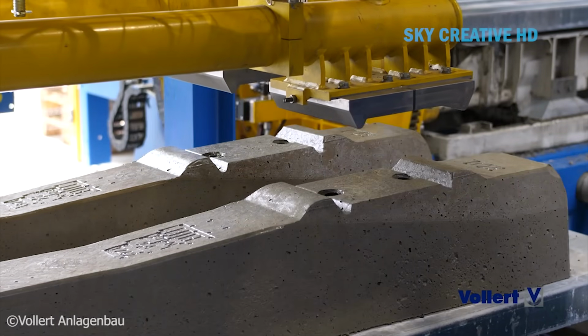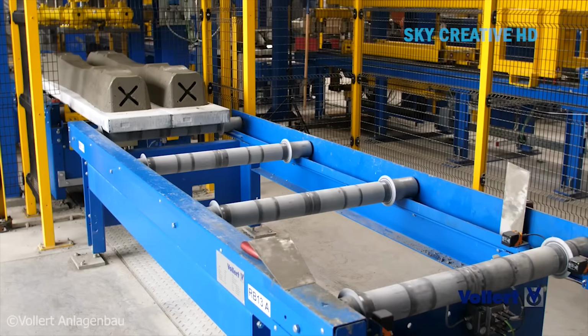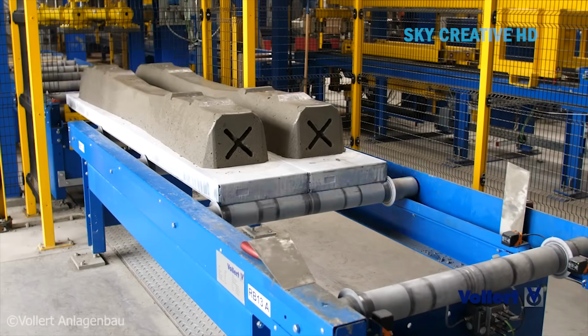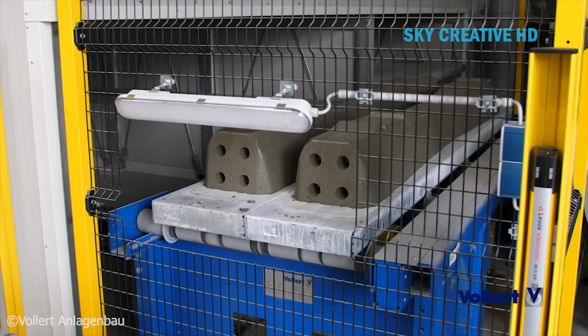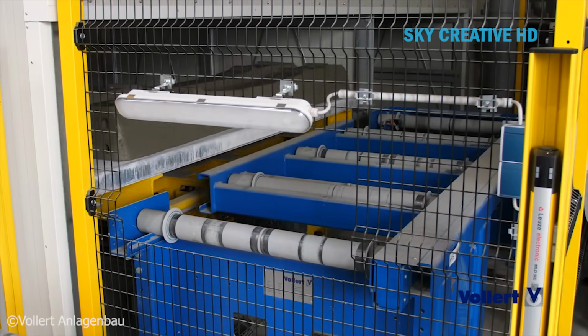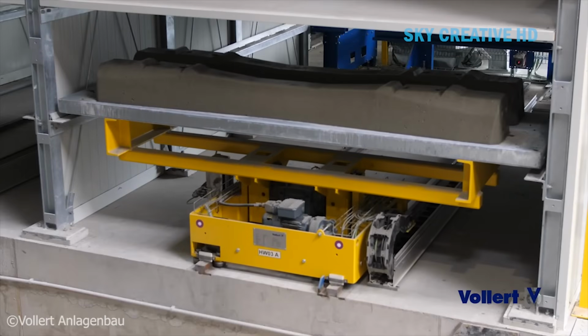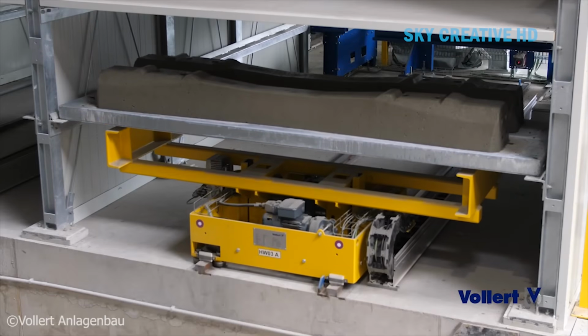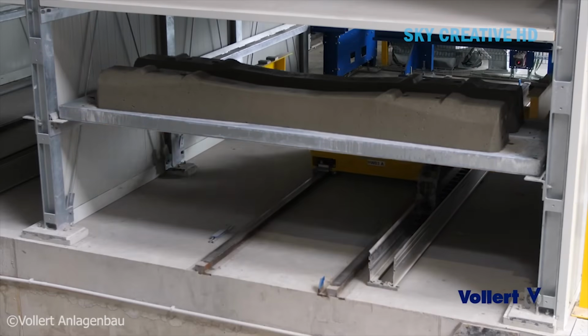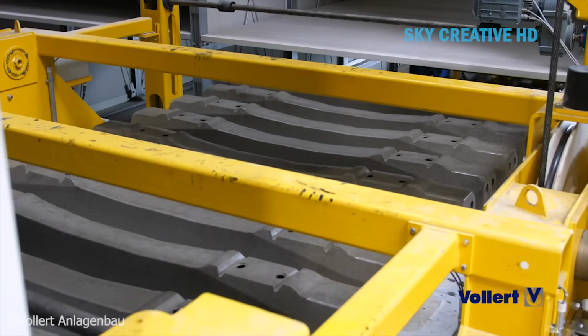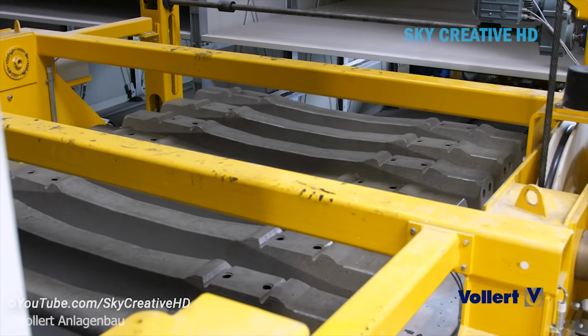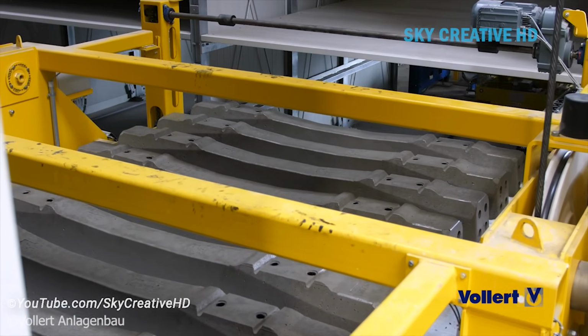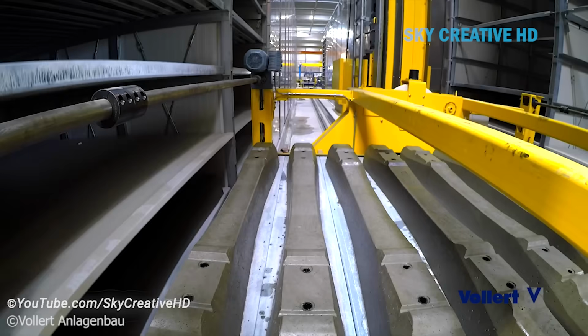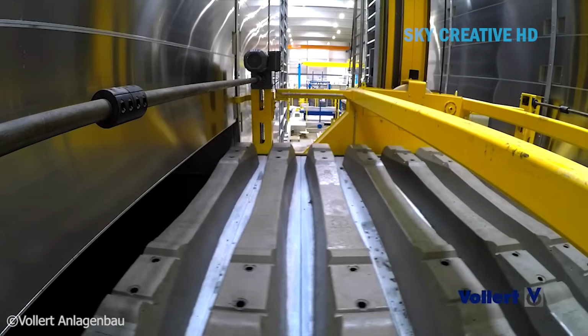The concrete pouring process uses a sophisticated distribution system that fills each tie mold uniformly. What's remarkable is watching the vibration process. Powerful pneumatic vibrators eliminate air pockets while ensuring the concrete flows around every detail of the reinforcing steel. The frequency and amplitude are precisely controlled. Too little vibration leaves voids. Too much causes the concrete components to separate.